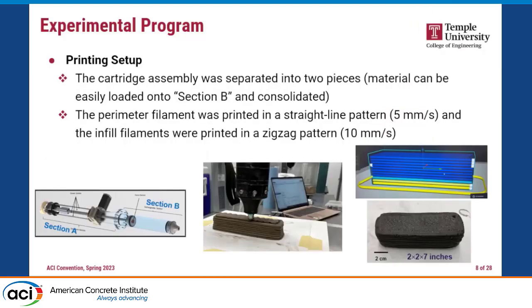This is our printing setup. On the left side, you see the printer. We designed the printer in a way that we have a plug-in system. Basically, we can plug it off easily, load the material, consolidate it, and put it back. This gives us a lot of flexibility in the open time, so it extends our open time. Here you see an example of the printing. As I said, 2 by 2 by 7 inch. So we can cure them, and we can cut them for compression or flexural experiments.